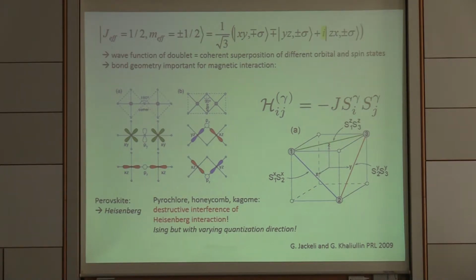Now, the wave function of this J-effective 1/2 is written here, and it has a coherent superposition of different orbital and spin states, and it has a complex component. And that now makes for new magnetic properties when those electrons hop between neighboring sites via oxygen 2p states, that can give rise to a very new kind of magnetic exchange. In particular, it was pointed out by Jackeli and Khaliullin that for the edge-shared IrO6 octahedra, we have a destructive interference of the in-plane exchange if we have 2 iridiums in the xy plane being connected by oxygens in the xy plane, and only the exchange between the z components of these pseudo-spins remains.